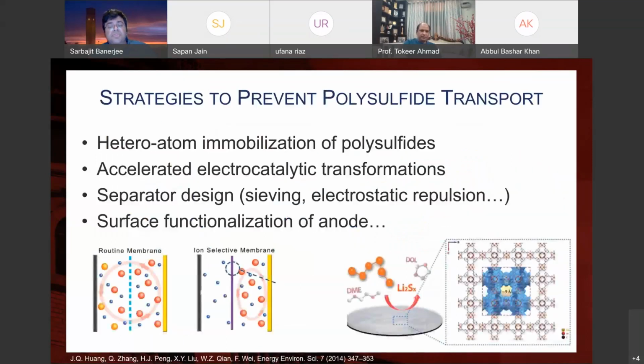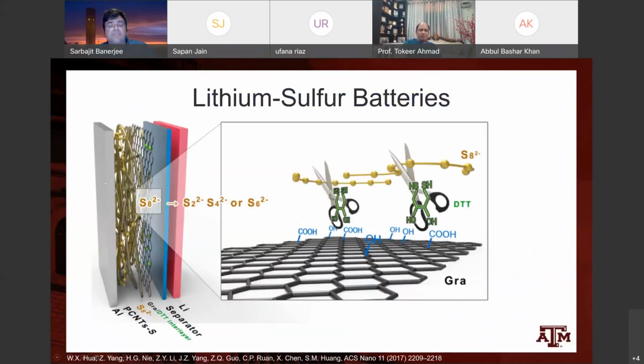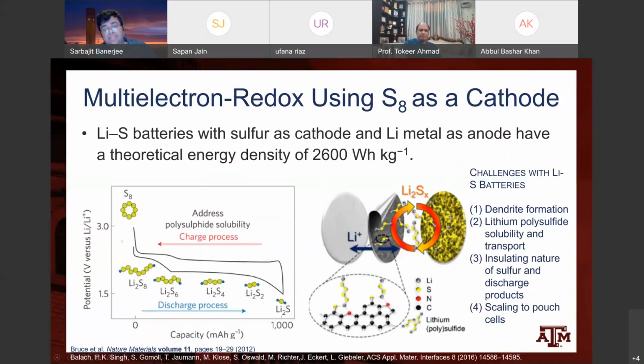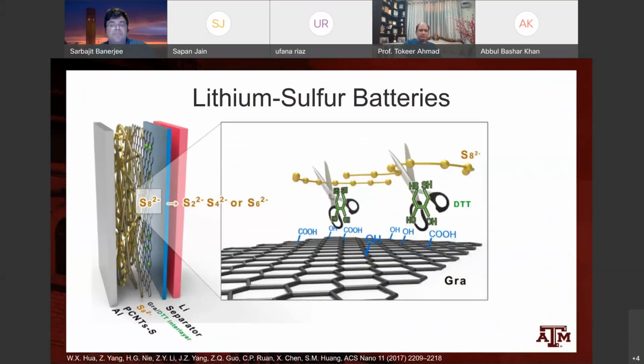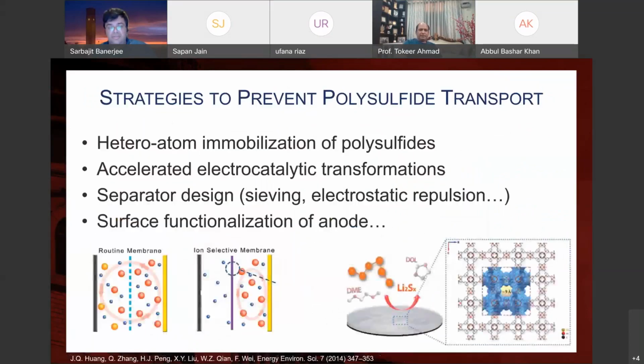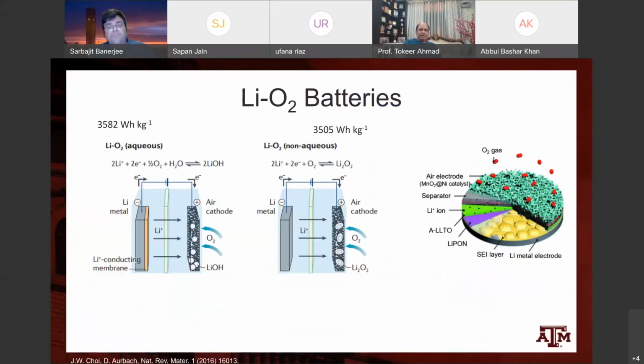So having a good separator that can control sieving, that brings in electrostatic repulsion. These are all issues. Another pretty nice approach that different groups have come up with is accelerating the transformation of polysulfides into the insoluble products, trying to get there as quickly as possible so you don't have a chance of these polysulfides being leached out of the mesoporous cathodes into solution, right? Okay, lithium air batteries, again, very promising, a fantastic concept, but still lots of challenges that remain.